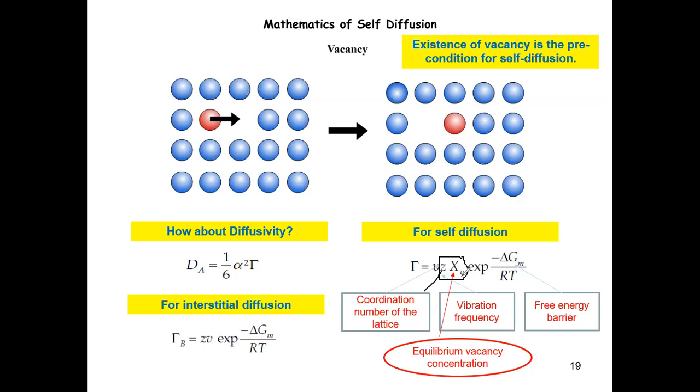And then basically now what do you have? If you didn't have the vacancy concentration, you have the hopping rate for a normal interstitial diffusion, right? And now you have to multiply a very, very, very small number to this hopping rate. So what are you going to end up with? A very small diffusivity, right? In general, a very small diffusivity.